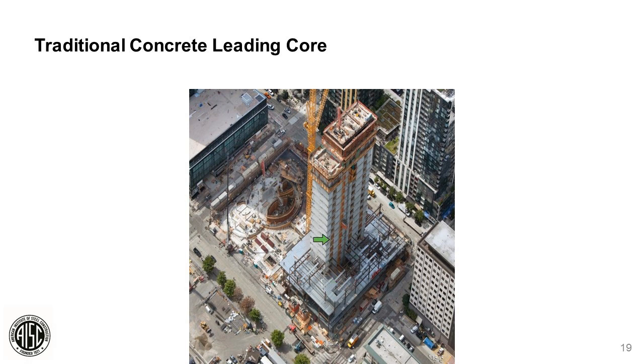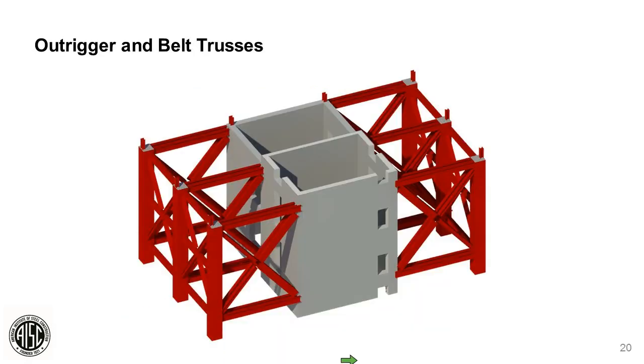So here's an example of a 40-story building. The core was jumped up about 20 floors, and then the steel erector mobilized and met at the roof. What we find on Rainier Square was we have this very intricate and detailed and steel-heavy structure that's occurring at this two-thirds point. This two-thirds point is strategic in its location. It's the delineation between the office floors below and the residential floors above. And this is an ideal location to put in that additional structure to get the building stance that we need to resist seismic and lateral forces. But the amount of steel here and the demands on the core in this region really drove the schedule.